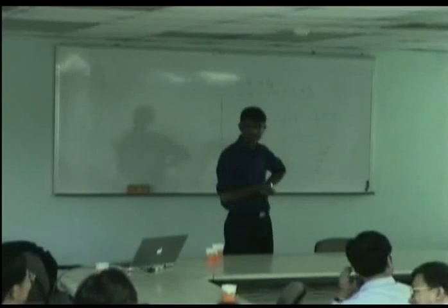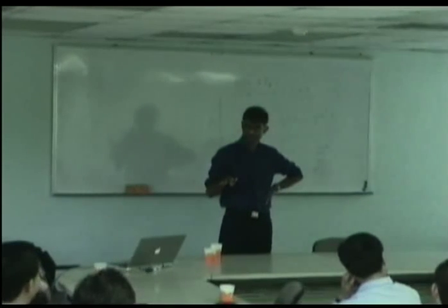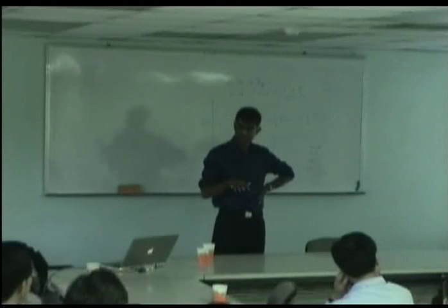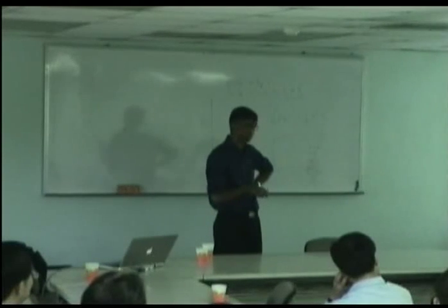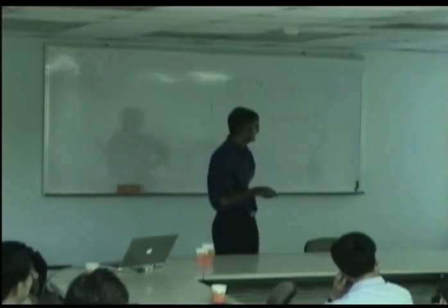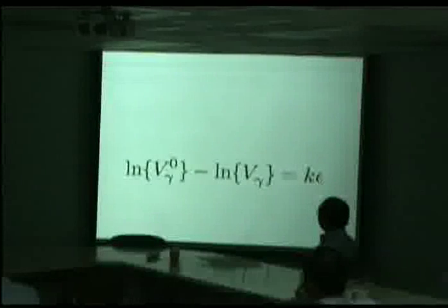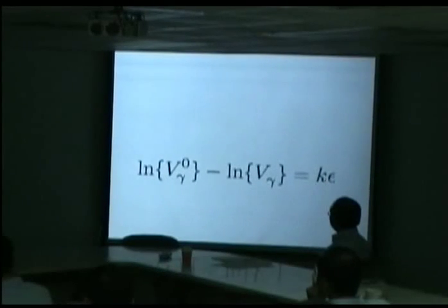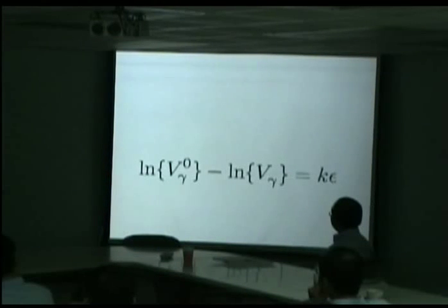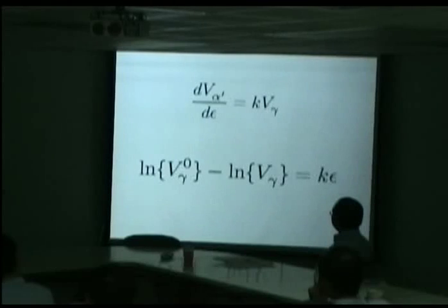This is the equation that's widely in the literature. Sugimoto, in particular, has used this equation. This is the starting fraction of austenite, and this is how much austenite remains as a function of the plastic strain. And there's a constant K here, which is different for every steel. Now, that will tell us how stable the austenite is as a function of strain.